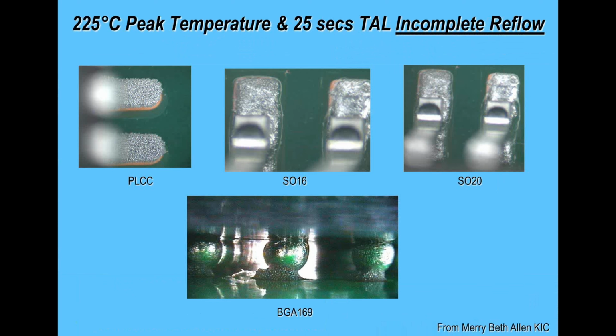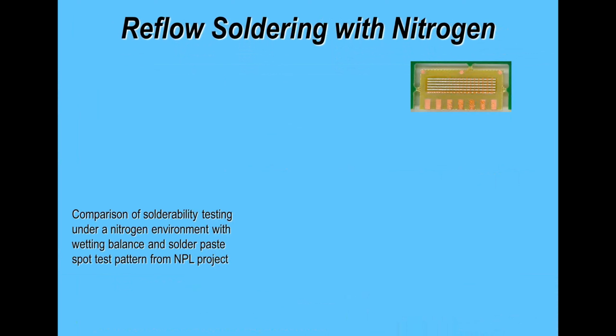Now again, the peak temperature and the time at peak temperature will have an impact on reflow soldering, but if you profile correctly, it shouldn't. And these are just examples where you haven't got complete reflow, and it's normally pretty obvious. I've just showed a PLCC, an SOIC, and a BGA, and these photographs were actually from Mary Beth Allen from KIC in the US, but it just shows the sludgy appearance or the incomplete reflow appearance of the solder. You can normally tell this when you look at high magnification, and clearly on the BGA on the bottom image the paste hasn't reflowed at all. It's probably got close to reflow temperature but not reflowed.